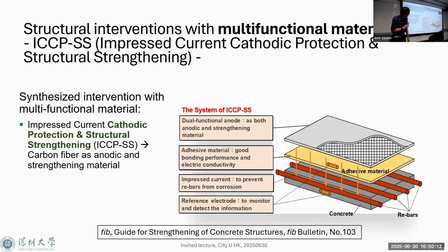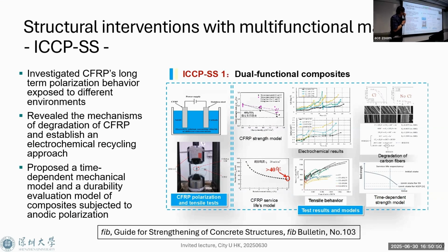For this particular case, using carbon fiber fabric, we can achieve structural strengthening, like the strengthening I have been talking about, and also it can be used for cathodic protection. So, dual function. Then we conducted many experiments to prove cathodic protection does work, but we have some degradation, due to ICCP, impressed current, which deteriorates the carbon fiber itself, in fact. But fortunately, once you have a chloride environment, the deterioration becomes much less. It's good news.